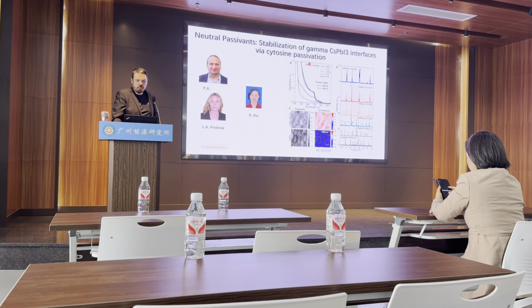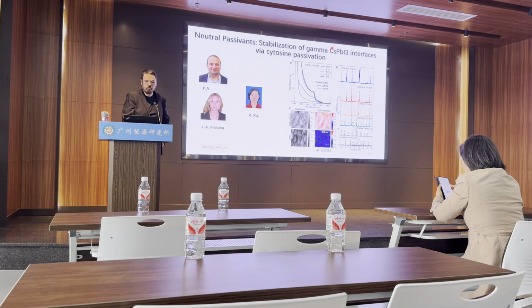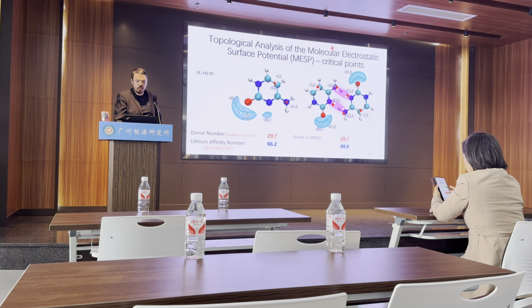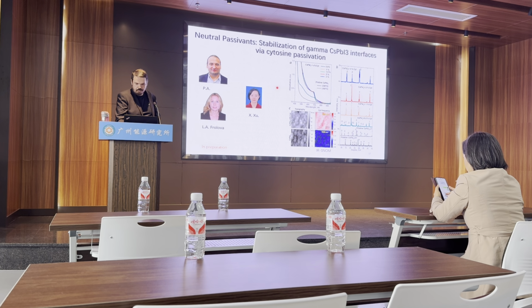So the final section is about the neutral passivators. This is the only paper that's unpublished. So the whole thing Luba wants to do is stabilize the inorganic perovskite. It has a lot of advantages, but it's phase unstable, so it degrades to the yellow phase very easily. So how do we stabilize it? The idea was cytosine, and basically when you add cytosine, the experiment does find that the inorganic perovskite starts becoming more stable.